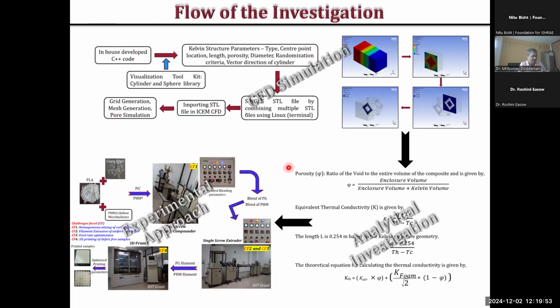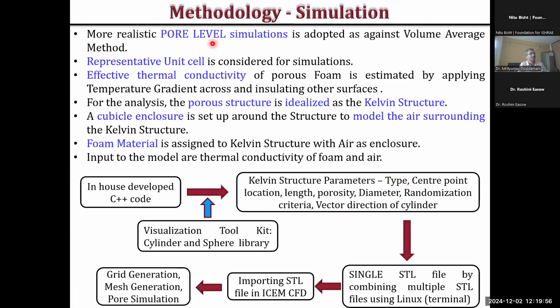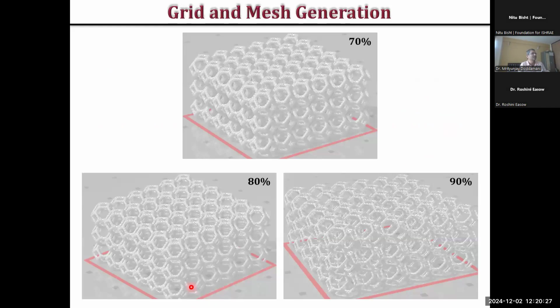About the first one, the CFD simulation, what we did was a pore level simulation. We took a unit cell and tried to find out the effective thermal conductivity. For the porous structure, we chose the Kelvin structure, which is the best as far as thermal conductivity is concerned. Then we modeled that. We took a cubical enclosure, modeled air surrounding it, followed the methodology and generated the grid mesh, and then finally did the pore simulation. This is how that Kelvin structure looks like. These are single unit cells of the Kelvin structure.